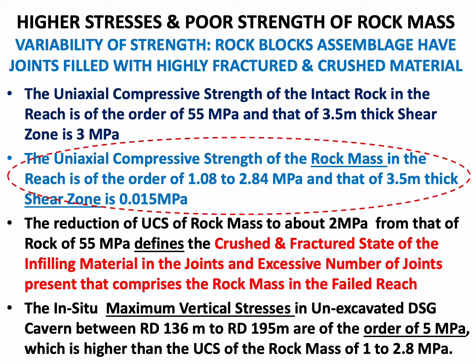The in situ maximum vertical stress in the unexcavated downstream surge gallery cavern between 136 to 195 meter RDs was of the order of 5 MPa. And this 5 MPa is in itself higher than the UCS of the rock mass, which is 1 to 2.8 MPa. So initially also, the entire rock mass was under a condition of stress of 5 MPa as compared to its rock mass strength of 1.1 to 2.8 MPa.